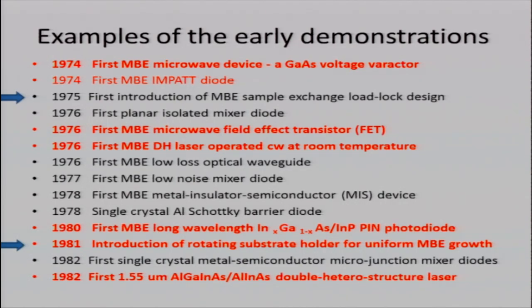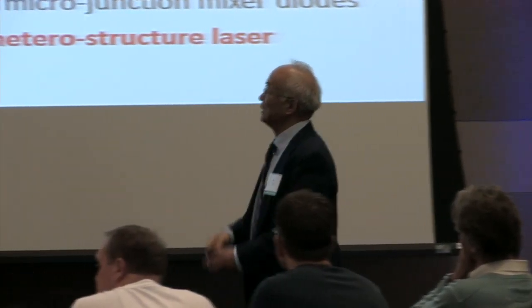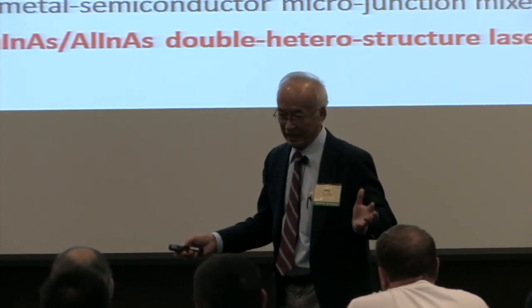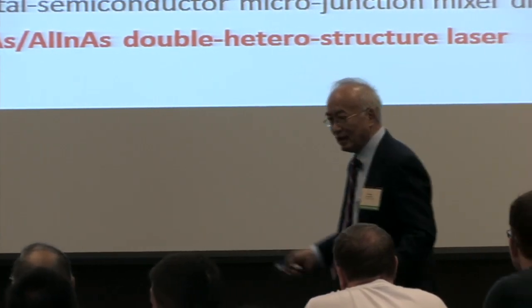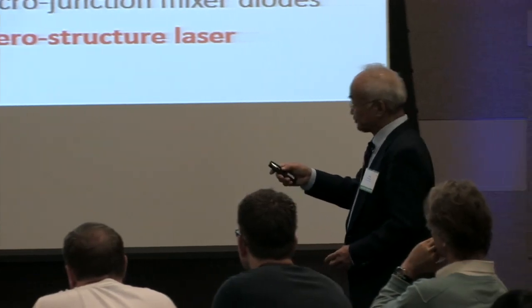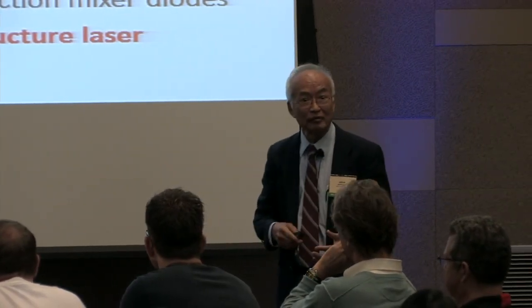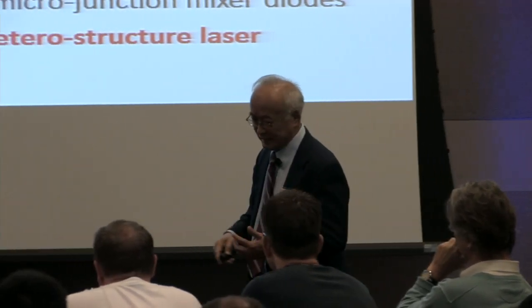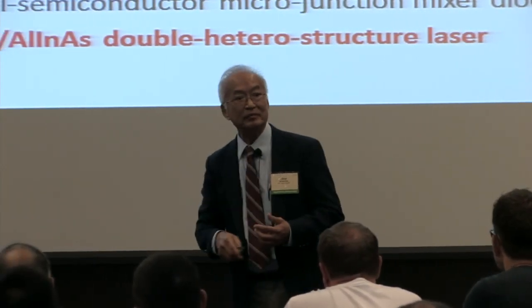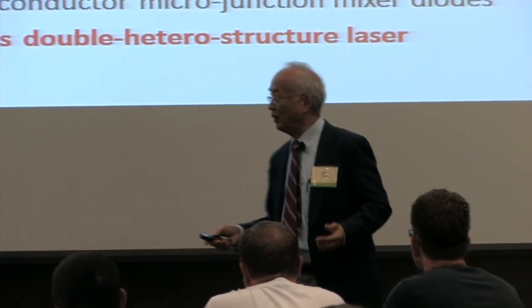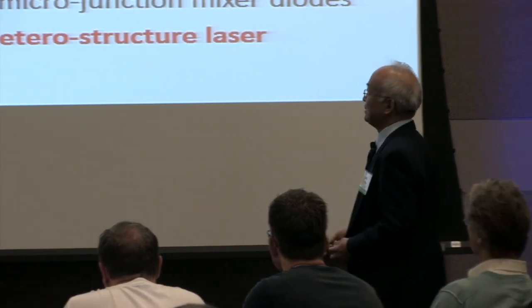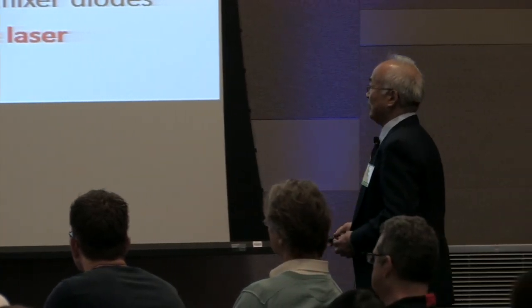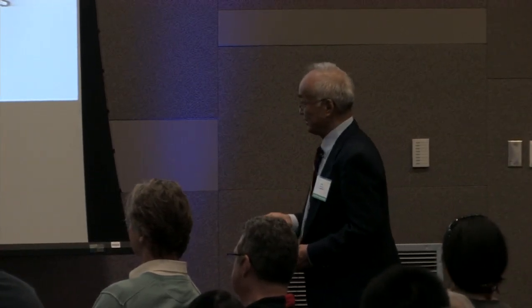If you can do that, you can almost practically do any other devices, because it's most critical to make those CW room temperature lasers. And then we continued to develop MBE. By 1980, we went into long wavelengths with Norman Chan in my lab, growing indium compound materials. And then we needed more uniform growth. With Norman Chan in my lab, we demonstrated the first rotating MBE substrate holders to get more uniform growth. And then we continued to make the 1.55 micron aluminum indium gallium arsenide double-heterostructure lasers, at room temperature.